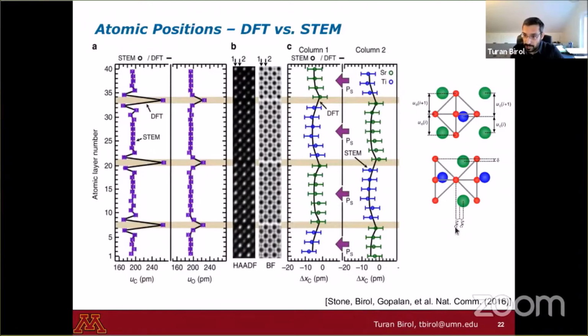So if you consider the crystal structure here, where the red atoms are the oxygens, there are these quantities delta, delta x_O, delta x_C, etc., which are all non-zero. And what we did was we compared these quantities, so these positions of the atoms, from theory and experiment. On the left, you see the position in the vertical direction. The black lines are the DFT results, and the data points with the error bars are the STEM, the experimental results.